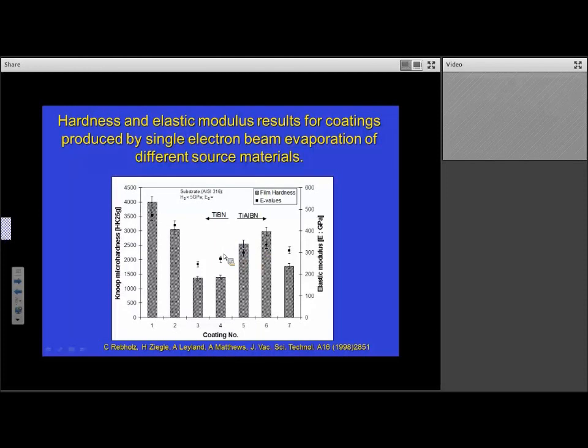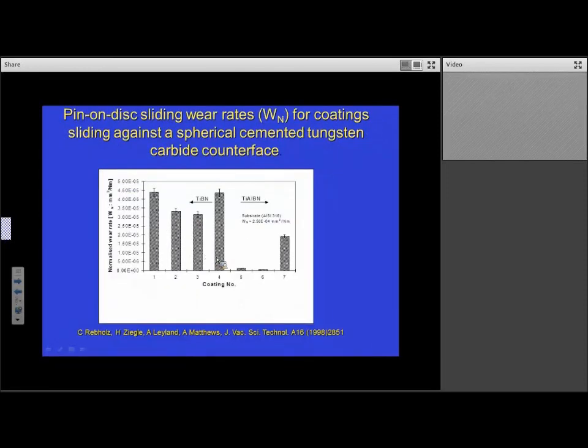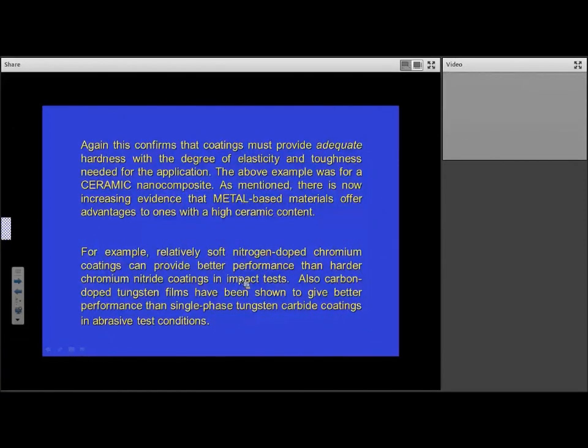And sure enough, as you might expect, when wear tests were done on these, it was those which had the highest ratio of hardness to modulus which performed best in those tests. So that confirmed that coatings must provide adequate hardness with the degree of elasticity and toughness needed for the application. And the previous example was for a ceramic nanocomposite. But as I've said, there's now increasing evidence that metal-based materials offer advantages to those with a high ceramic content.